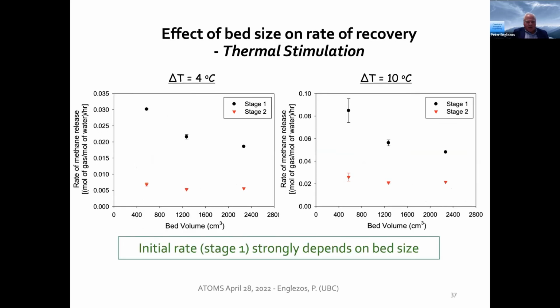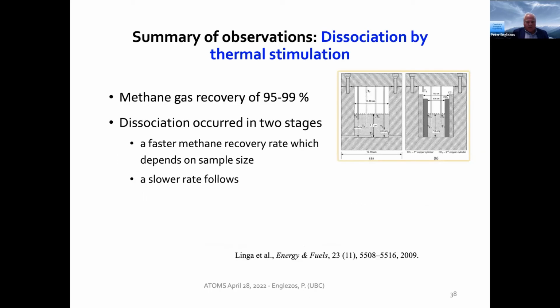This two-stage process is interesting in that the stage one process depends on the size of the bed, as you can see, but the second stage becomes independent of the bed size. So the size matters with respect to the early stages of dissociation.